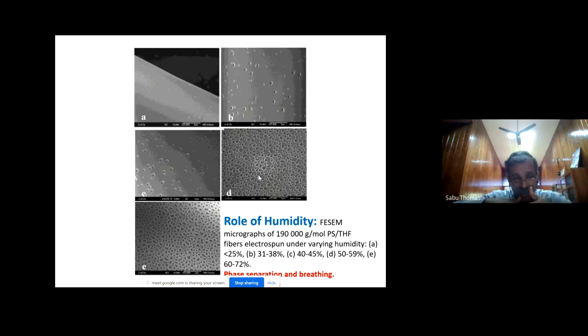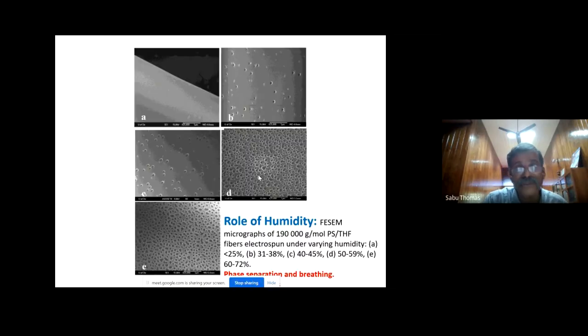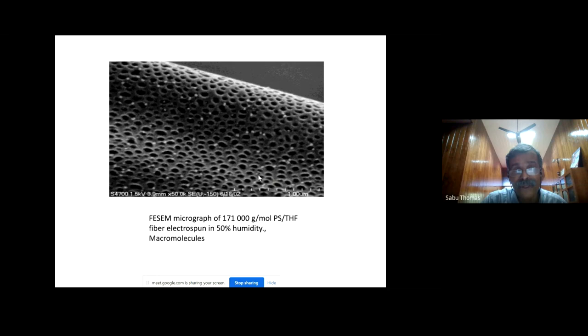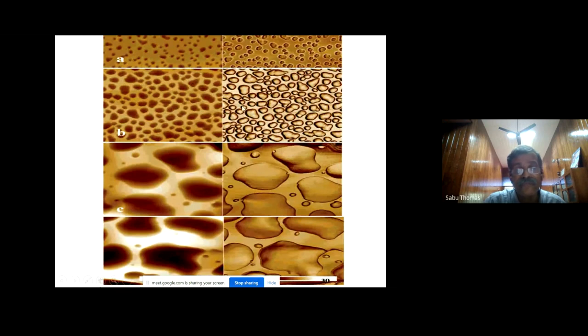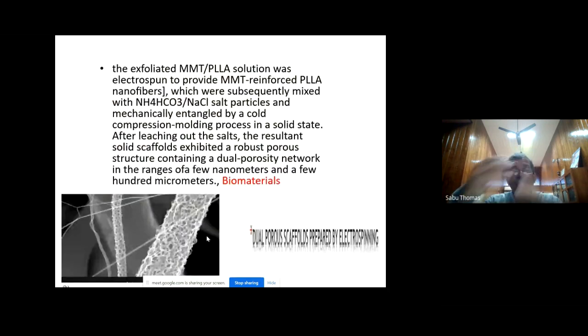When you do the electrospinning process, the solvent evaporates from the fiber. Therefore, the surface gets cooled. Then what happens when the surface gets cooled? The water vapor in the electrospinning chamber undergoes condensation. It condenses on the fiber surface and makes an impingement. That is why you have lots of holes. So you can make nanopores on the surface of the electrospun system by controlling the moisture. You can see a beautiful AFM picture. Pores on the nanofiber. You can also make dual porous structures.